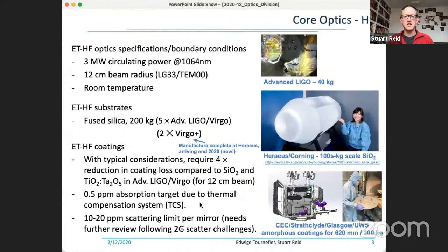Thermal compensation system is probably going to limit the permissible absorption in the coatings to around 0.5 parts per million, and scatter has been set within the design to be 10 to 20 parts per million. But again, one of the motivations at this stage within the Einstein Telescope Consortium is the system integration and how we link all the components together. And the fact that scatter has been a major challenge for the second generation detectors, clearly we're going to have to look into this in detail.